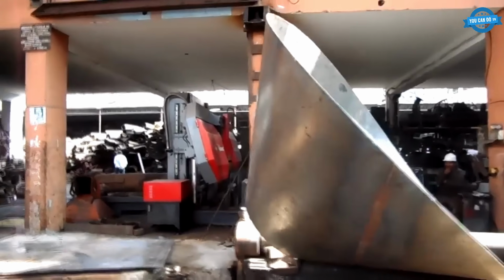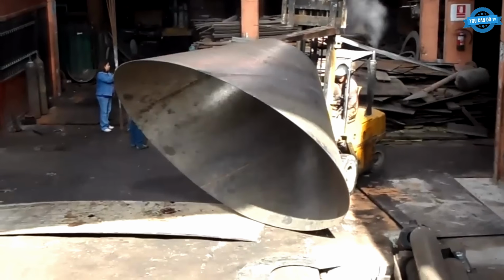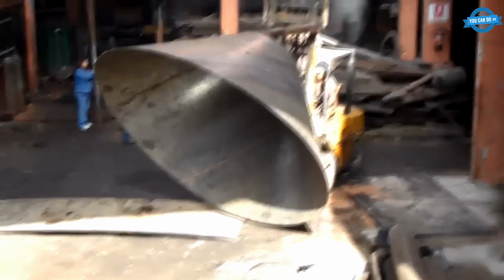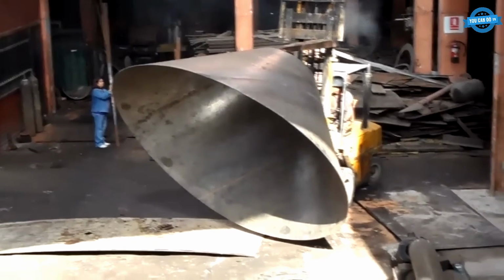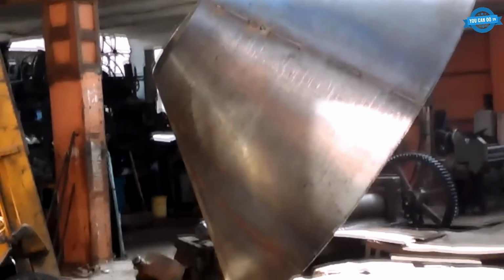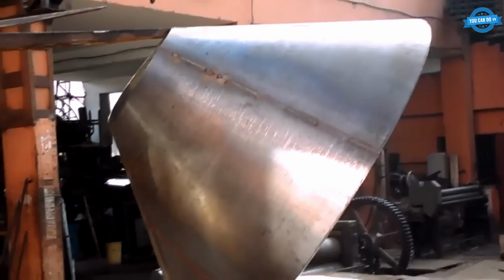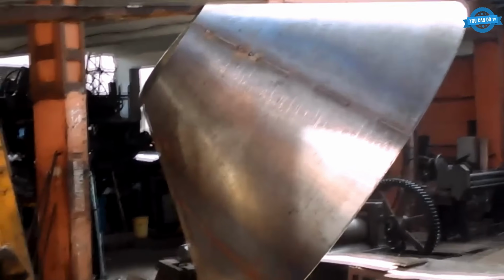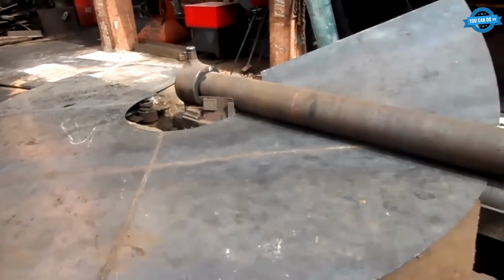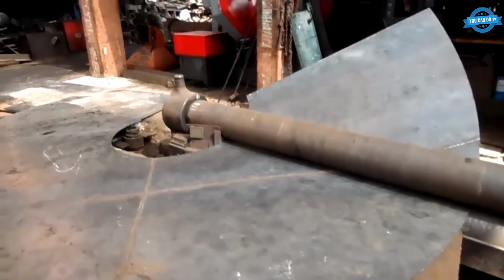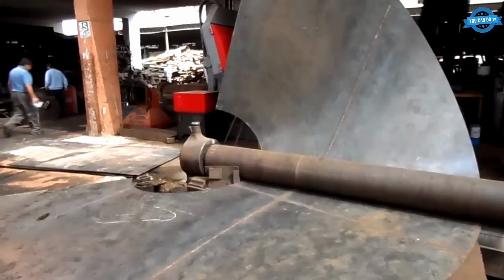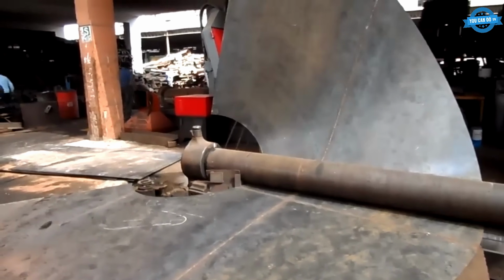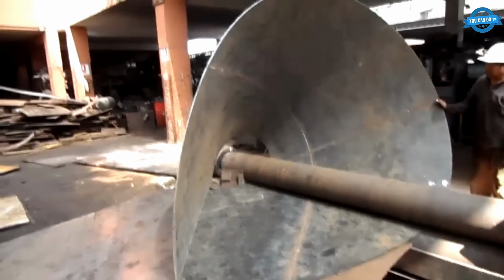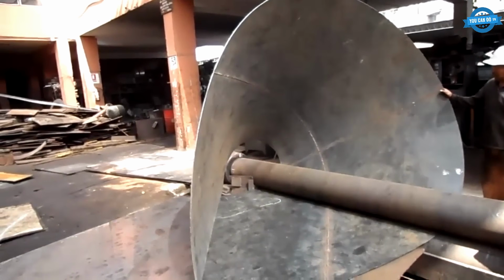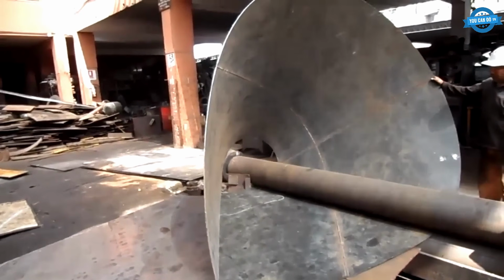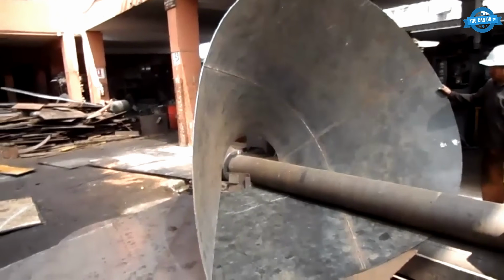Rolling a 4.5 meter diameter cone, wide at one end, narrow at the other, is roughly twice as hard as rolling a cylinder of the same size on the same machine. A cylinder has one radius along its length. A cone has every radius between 2 endpoints, distributed along the same plate. The plate enters the rolls cut to a developed pattern that looks nothing like the finished part. The bottom rolls tilt asymmetrically to feed the wide edge faster than the narrow edge. As the cone forms, the operator constantly adjusts roll position to keep the geometry true. One plate, one heavy machine, and one finished pipe section.